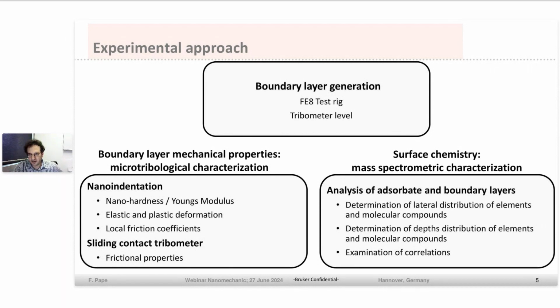And a lot of work has been done in the past 2 decades together with the colleagues in Münster, the group from Professor Benninghoven, with the time-of-flight secondary ion mass spectrometry to analyze the adsorbate and boundary layers, the distribution of elements and molecular compounds, and also the depth distribution of these elements by sputtering away some amount of the surface and then investigating the distribution of elements again.